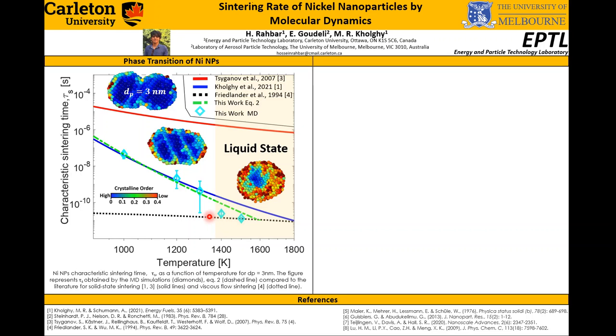As you can see, for nanoparticles with a diameter of 3 nanometer, at temperatures below 1100 Kelvin, particles are fully solid. The results from MD simulation and the proposed equation nicely reproduce the results obtained from phenomenological models. As temperature increases, the MD-derived characteristic sintering time deviates from the literature. This implies that the surface melting has started. Finally, at high temperatures above 1400 Kelvin, we can see that particles are fully melted.